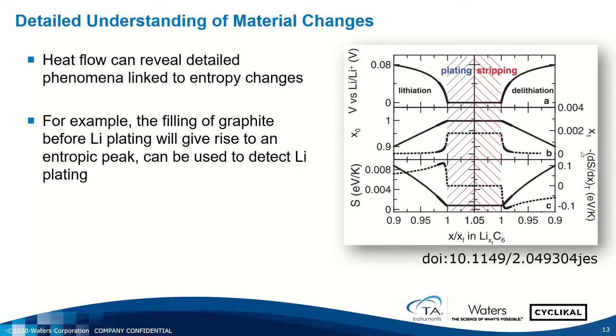So in the calorimeter, what I'm measuring is the derivative of the entropy with respect to stoichiometry. I have this rapidly varying entropy, then it suddenly becomes flat, and that shows up as a peak in my heat flow. So lithium plating will have a signature in the calorimeter, and lithium plating is often a source of failure in cells, and it's also very difficult to measure. This is one of the only ways that you can detect lithium plating in situ without having to take apart the cell.